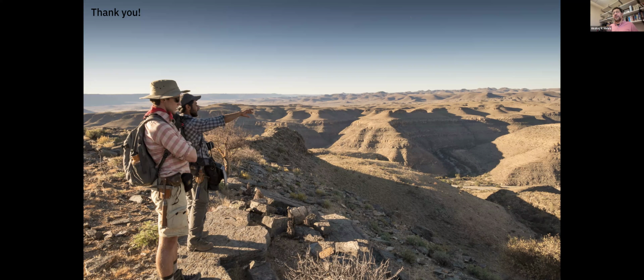I argue maybe in certain cases you can, if they are mineralogically distinct enough, or somehow materially distinct enough. But in other cases, for example when we're looking at modern ooids and trying to understand how multiple generations of cement may work on those ooids, you actually do need something that's optical or multispectral or even geochemical to really tell the difference between those. Those are places where the ooid itself and the secondary cements might actually look exactly the same in CT.